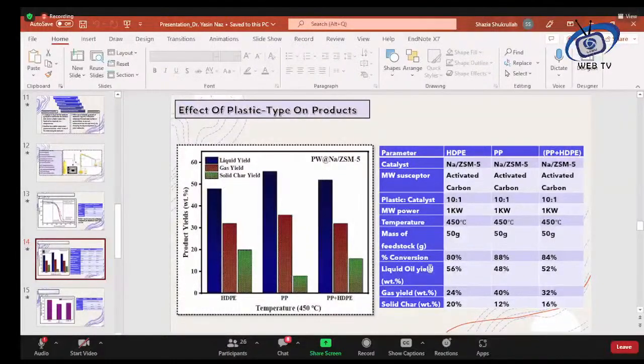Then we checked the conversion efficiency at 450 degrees Celsius. 80% of HDPE converted into liquid and gases, and the rest, 20%, was the solid product. Similarly, under the same conditions, 88% of PP changed into liquid and gases, and 12% was the residue, which we anticipate would be the structured carbon, I mean the carbon nanotubes.